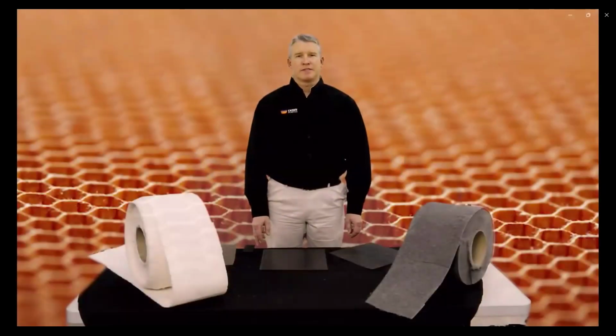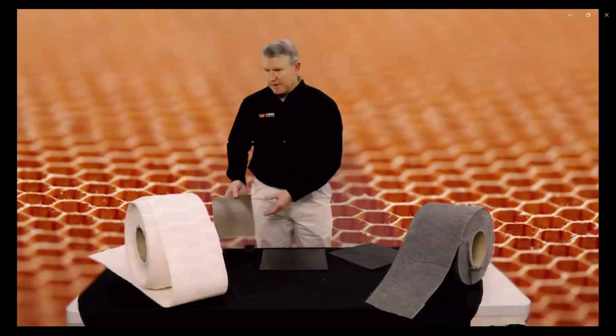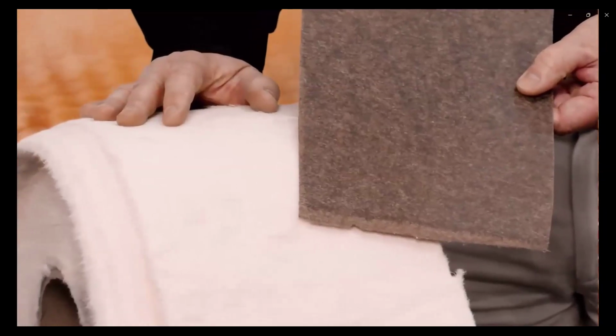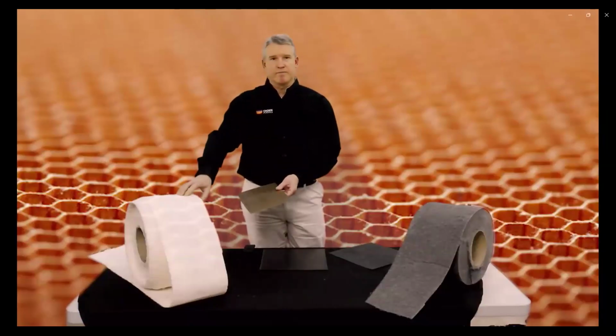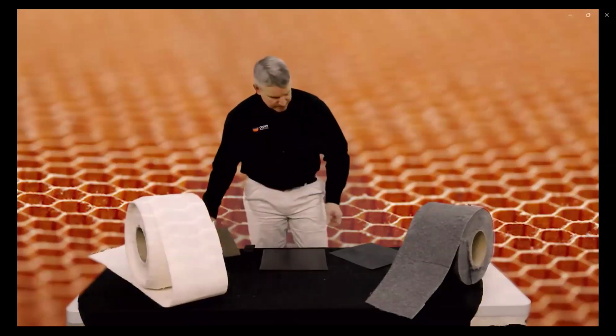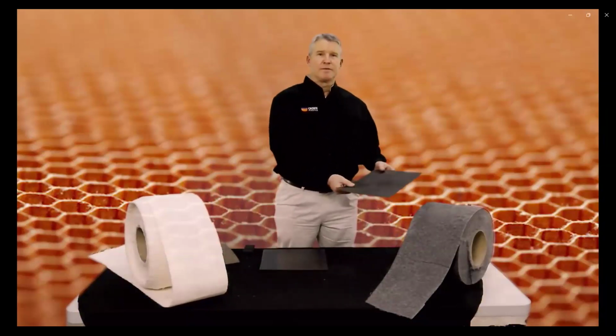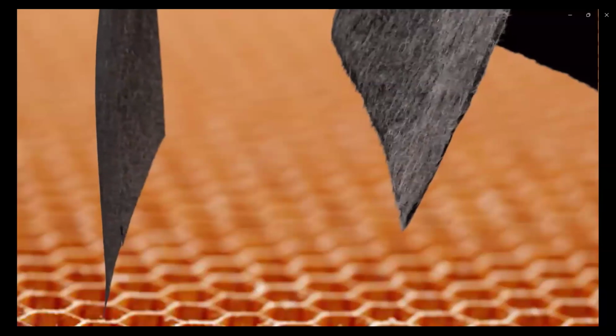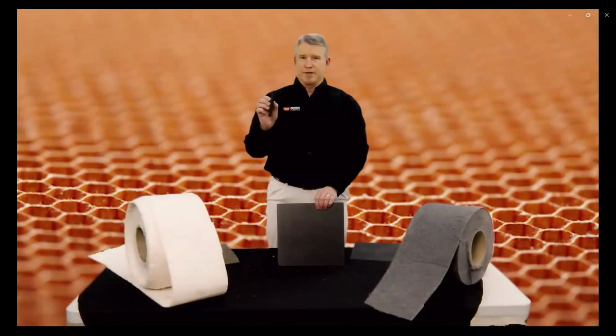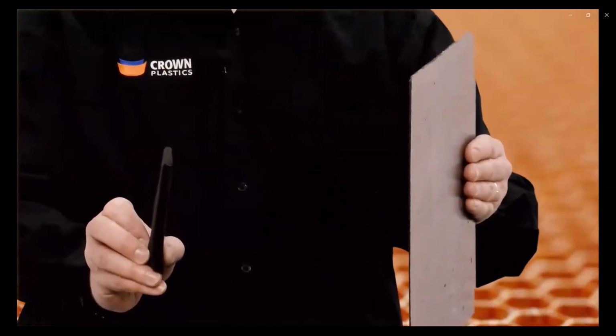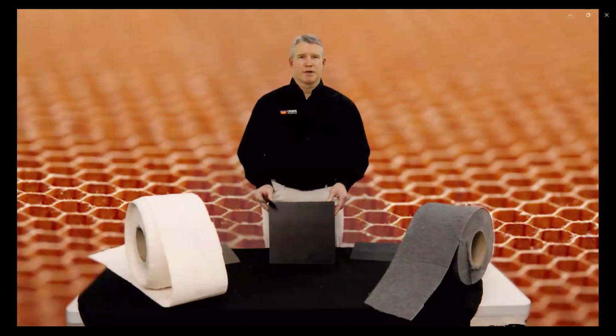Over the years, Crown Plastics has participated very heavily in the debulking and consolidation of nonwovens. This is an Ultem and glass material that has been debulked to this thickness from 2 millimeters to about 1. Here we have a PPS nonwoven in roll form that has been debulked to 0.5 millimeters. This is a nonwoven from 10 millimeters down to about 1 millimeter. The debulking of nonwoven materials is used very heavily in the aerospace industry for interior panels that Crown debulks and will later be thermoformed.